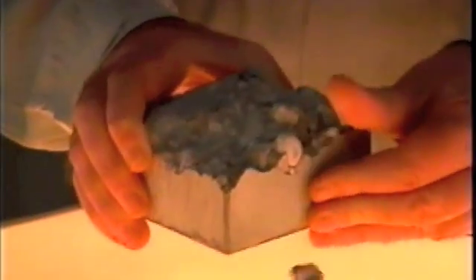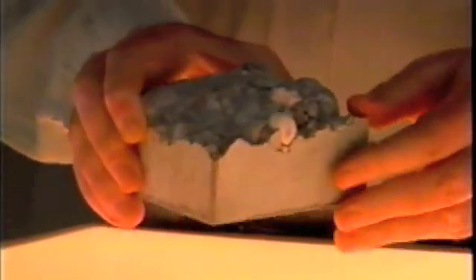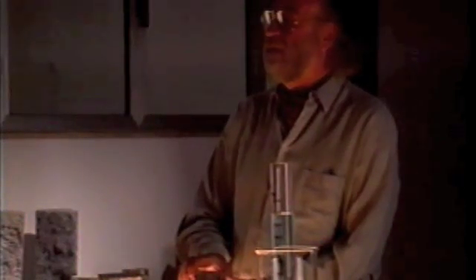When we add too much water, it gets between the cement grains and keeps them further apart. The fibers are less tightly interlaced and the whole material is more porous. The result is a cement paste with low strength, porous and permeable to water, as well as to the aggressive chemical agents to be found in water.